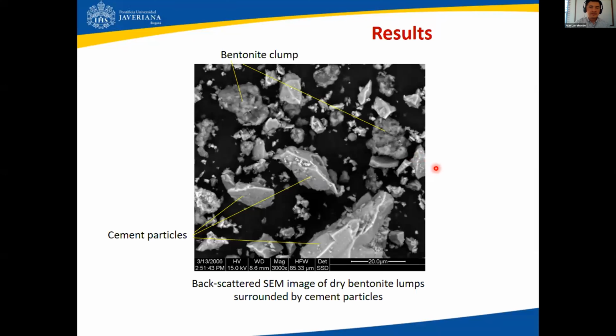Another thing that is very interesting to see in these photos is the relative size of bentonite clumps to cement particles. And what you can see here is that the Portland cement particles are actually silt size as well, and they are much larger typically than individual clay particles, and of course even larger than the bentonite aggregations. So this, we believe, is going to have implications in the chemical reactions that take place when this gets hydrated, because the cement particles being larger than the bentonite and clay particle units, probably the reactions are going to be heterogeneous. That doesn't mean that the reactions do not take place. Of course, they take place, but they are not necessarily like very fine powders combining and hydrating with one another. So this is important information to keep in mind.